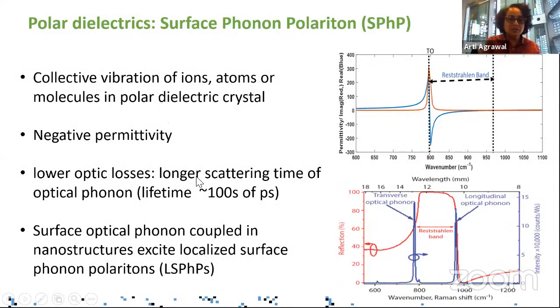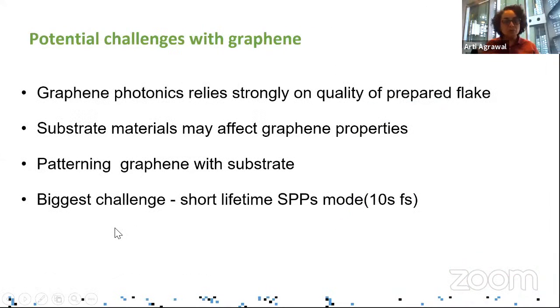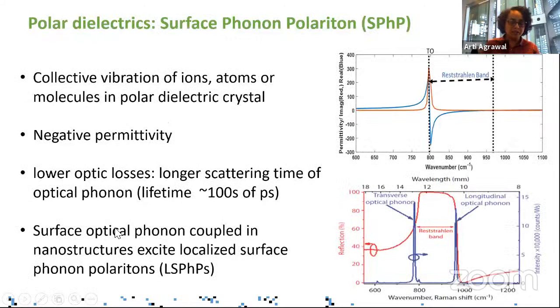On the other hand, with the polar dielectrics such as silicon carbide, we have certain other things which are useful. They have lower optical loss, and they have a longer optical phonon lifetime. So the lifetime here is a few hundred picoseconds, which is much, much better. And it is possible to pattern the polar dielectric. And therefore, by patterning it, it is possible to localize the phonon polariton resonance and then be able to play around with the manipulation of light and things like that.